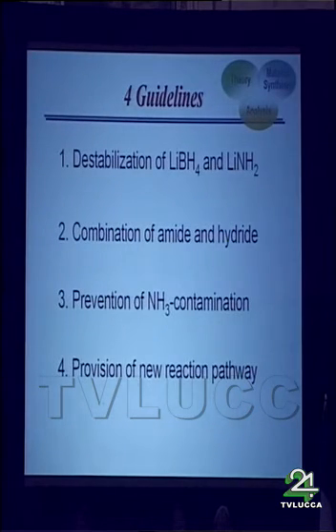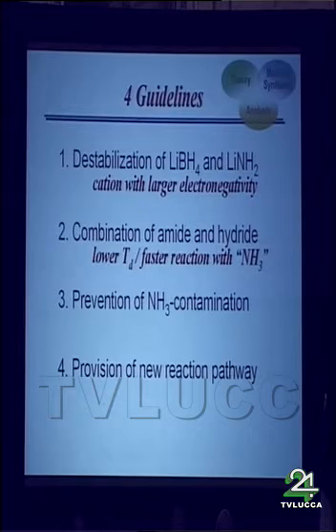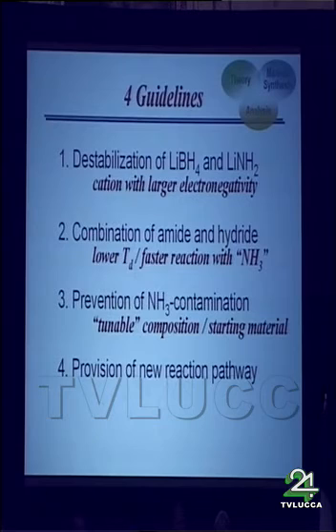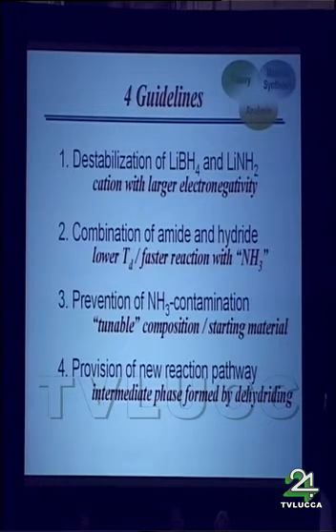Okay, as a result of the collaboration, we have obtained guidelines on these topics. First, cations with larger electronegativities are effective for the destabilization of the borohydride and amide systems. And second, one of the optimized combinations is an amide with lower decomposition temperature and a hydride having faster reaction kinetics with ammonia. And third, not only compositions but also starting materials are important for the prevention or suppression of ammonia contamination. And finally, I can say that it's important to estimate the intermediate phase formed by the dehydriding reaction for the effective provision of new reaction pathways.